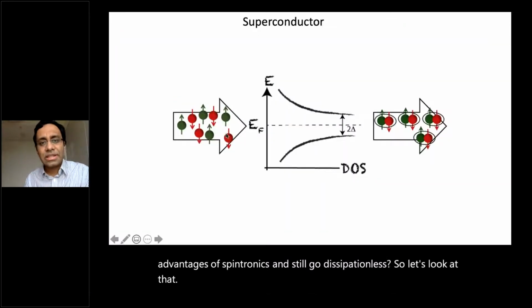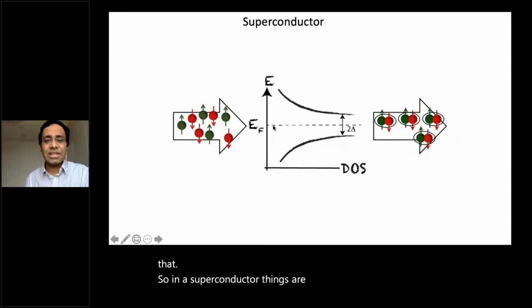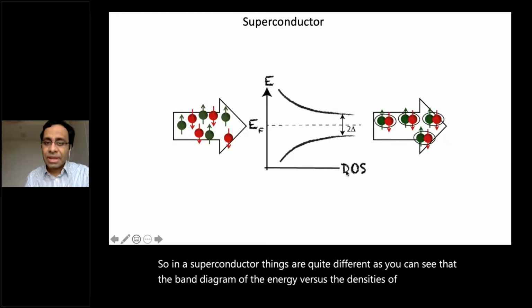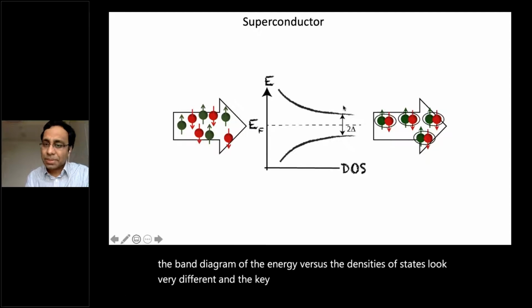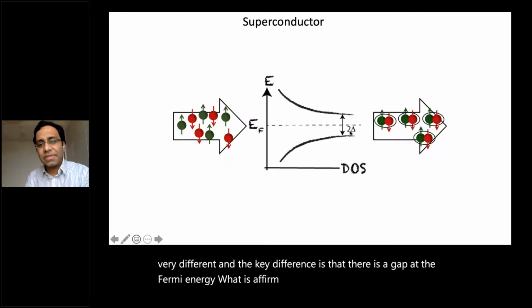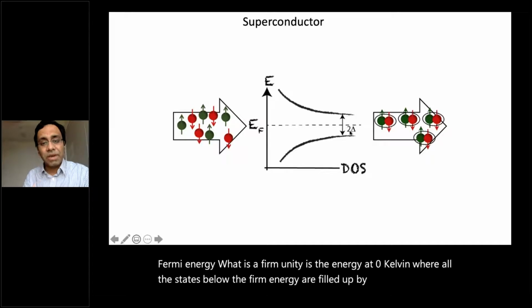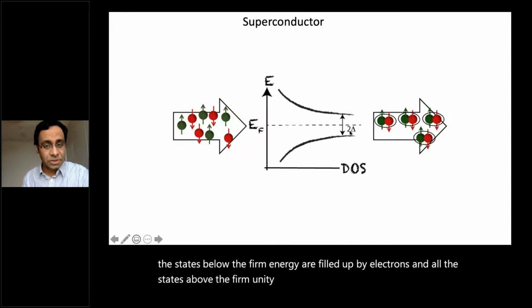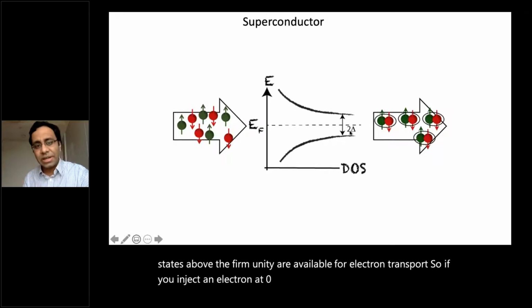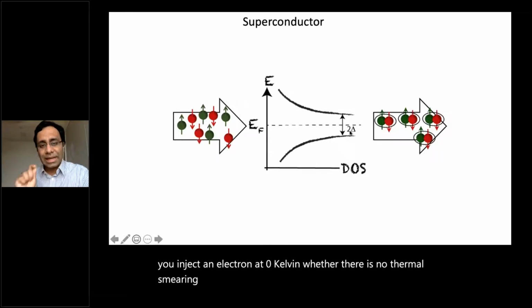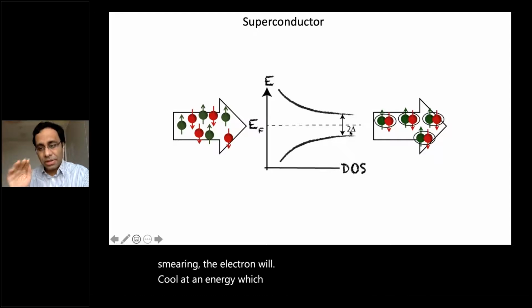So in a superconductor, things are quite different. As you can see, the band diagram of the energy versus the density of states looks very different. And the key difference is that there is a gap at the Fermi energy. What is the Fermi energy? It is the energy at 0 Kelvin, where all the states below the Fermi energy are filled up by electrons, and all the states above the Fermi energy are available for electron transport. So if you inject an electron at 0 Kelvin, when there is no thermal smearing, the electron will go at an energy which is higher than the Fermi energy because all the rooms below are filled up.